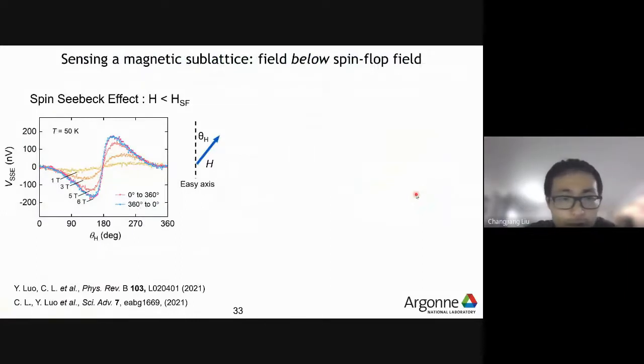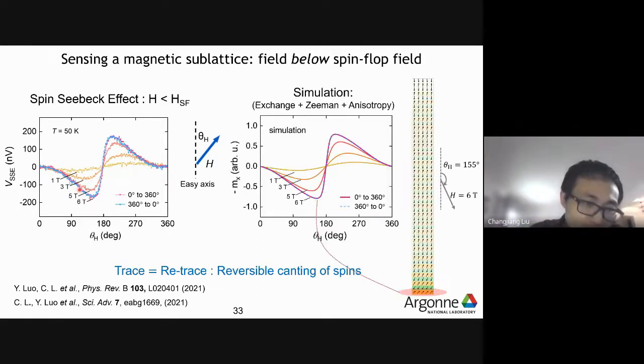So now, once we turn on the heater and apply a magnetic field, shown in this plot is the response measured in the platinum layer as a voltage as a function of the angle of the magnetic field. You see there are different traces, different lines of data points. These correspond to magnetic fields of different strengths from 1 to 6 Tesla. You see there is a sinusoidal shape, basically a gradual increase of voltage as you rotate the magnetic field.